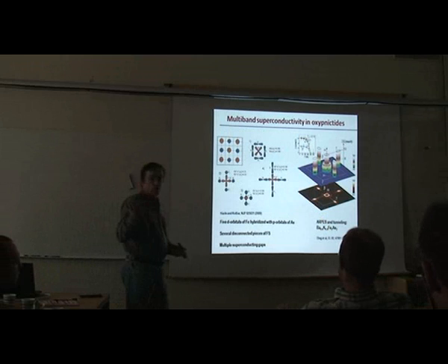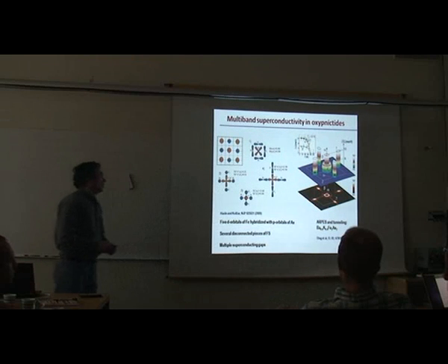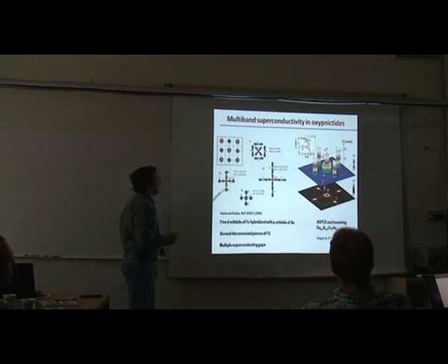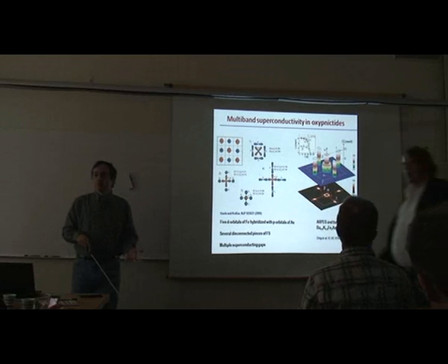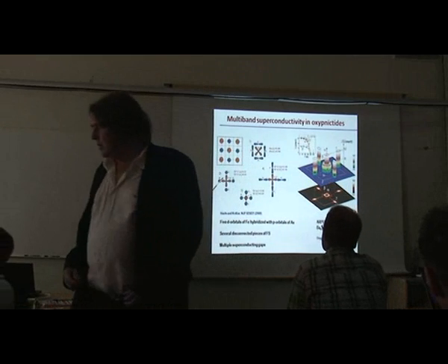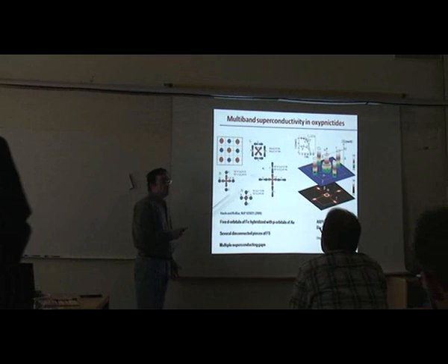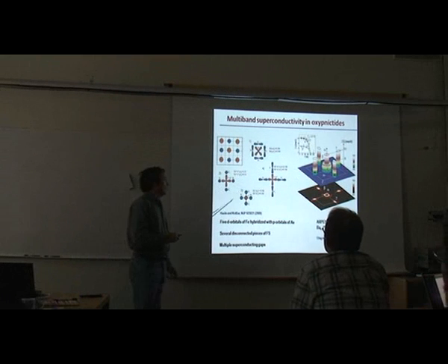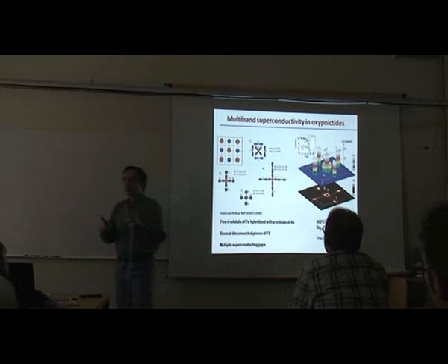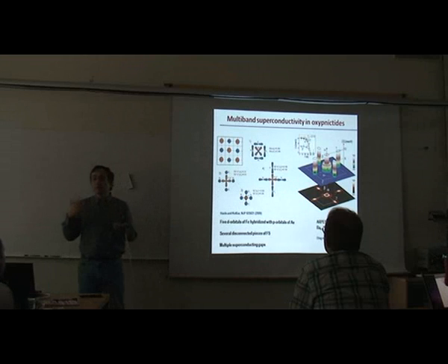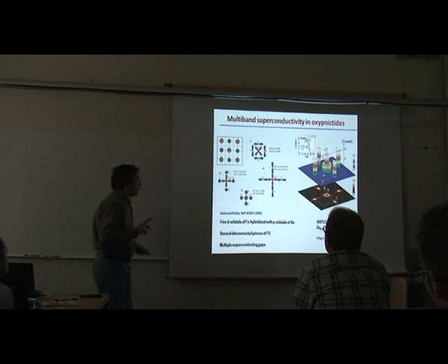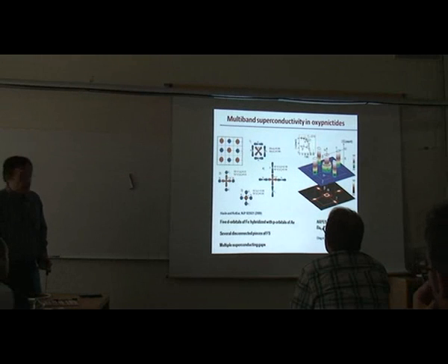So what about Fermi surfaces and mechanisms? This is a very complex material because what happens here is this. If we consider the iron arsenic plane, here's an iron ion, and it has 5 d orbitals. And those d orbitals are hybridized with the p orbitals of arsenic. So generally there are 5 different bonds, and those bonds produce 5 different bands very close to the Fermi surface. And that is important to keep in mind because that can produce a lot of unexpected things.